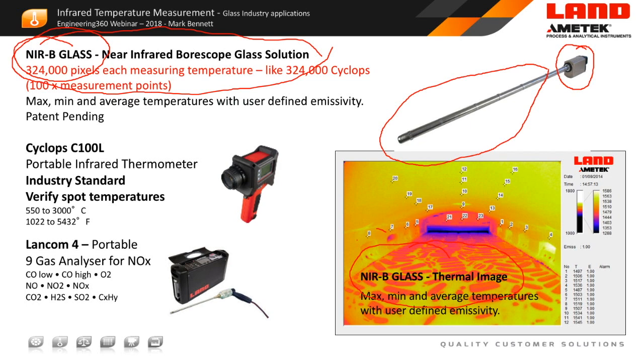And as you can see here, you can actually measure at any location continuously, either along the walls or anywhere on the refractory. And this allows you to capture very precisely the temperature in the tank at a given time during the flame out, between the reversal when the flame is not present. Now, we still use the trusted Cyclops as a cross-check, because the operators looking inside the glass tank and making these measurements, looking inside the tank is a very important part of the general process, just to monitor the condition of the glass tank.